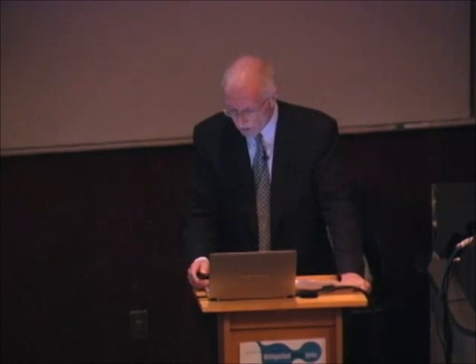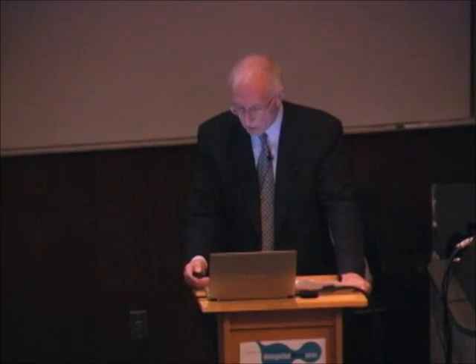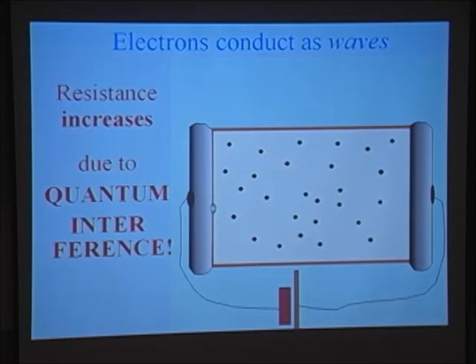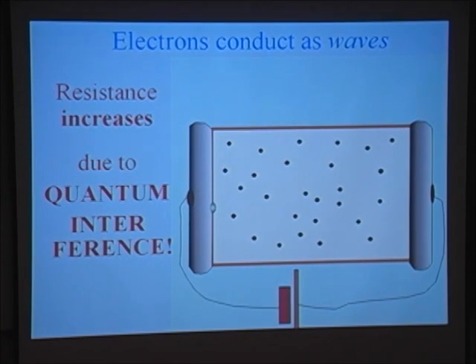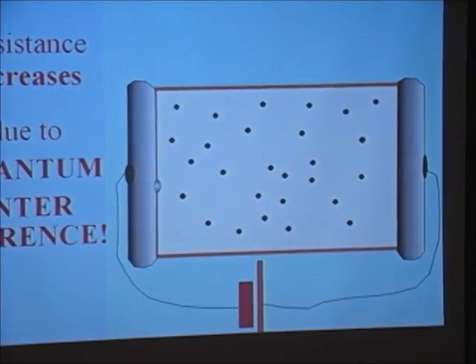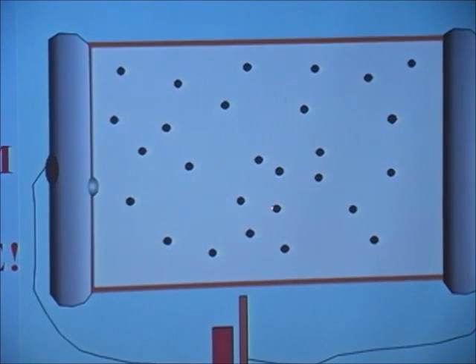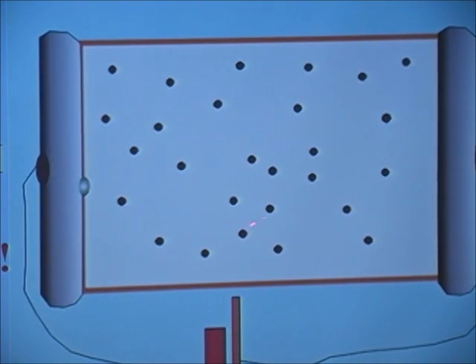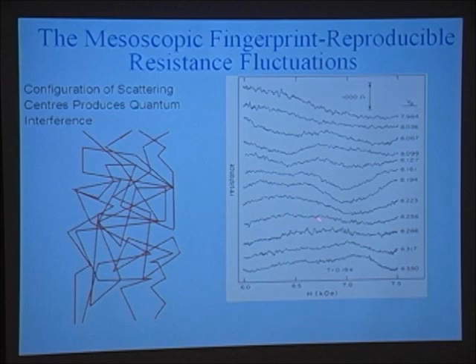This is the so-called mesoscopic regime, which is intermediate between the macroscopic and the microscopic. Here we have basically what happens. Now, at the moment, of course, this is an effect which is confined to low temperatures, because we're talking about quantum interference as a limiting feature of resistance. And what quantum interference is: we consider the electron as a wave, and the wave comes in and it's scattered by every impurity. So we can get the situation where the wave comes around and interferes with other waves. And this gives rise to a contribution to resistance, which is random as parameters change.